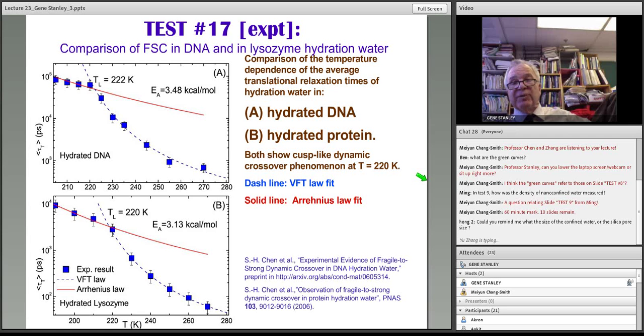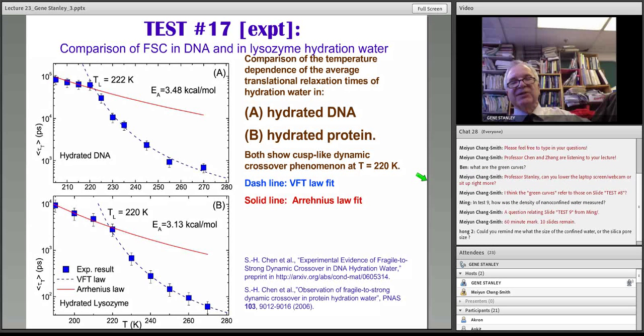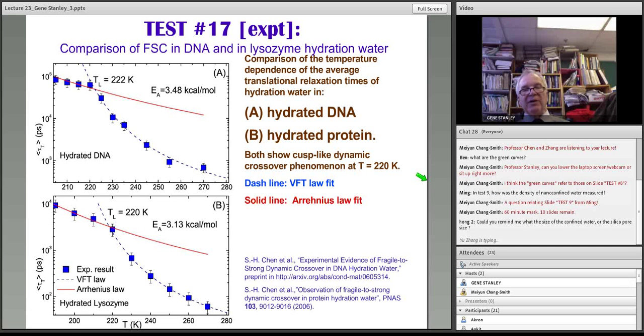And I see the second question from Hong is the size of the confined water or the silica pore size. I thought I said the silica when I showed 10 angstroms, 12, 14, 16, all the way up to 20 angstroms. So that tells you the pore size, and the properties were independent of pore size. So now when it's confined by a biological molecule, it's in a sense not really confined. It's just a layer of water, or of several water molecules, but it's not something with a uniform distance because it depends on which part of the surface of the protein you're at. A hydrophobic part may have less water around it, and a hydrophilic part of the protein may have more, but the key thing is that the amount of water doesn't matter. What matters is it does not freeze. To prevent water from freezing, you got to follow Linus Pauling, 1947, and bust up that hydrogen bond network.